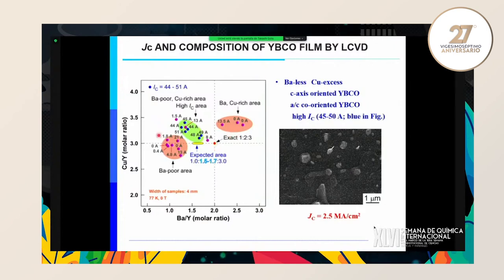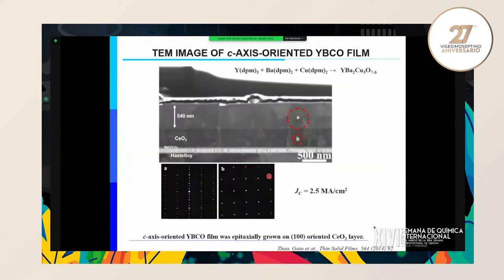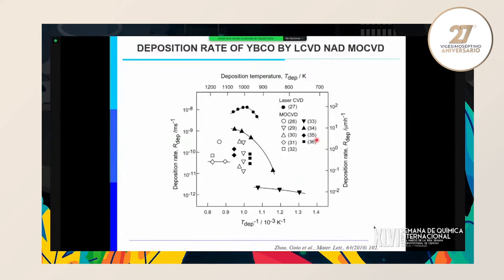This is the effect of gas concentration ratio on the critical current. By changing many conditions, we can find the highest critical current, 2.5 megaampere per square centimeter. Actually, this is slightly deviated from the stoichiometric composition of YBCO, with barium less and copper excess. A small second phase like this becomes a pinning site of magnetic flux for high critical current. And the deposition rate is almost 10 to 100 times higher than conventional MOCVD.